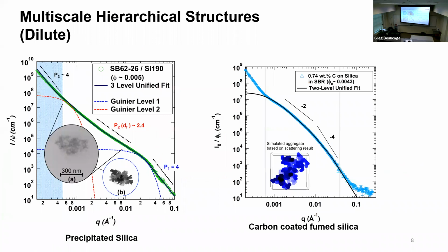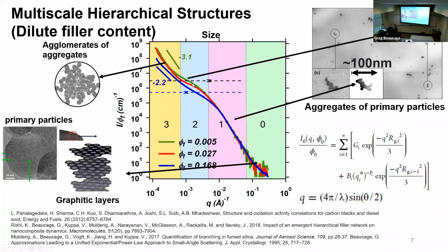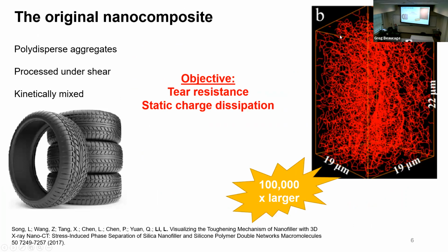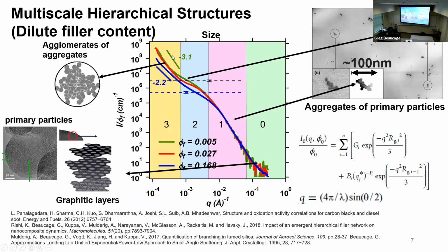Basically the aggregates overlap, that leads to this diminishment, and the speed of that diminishment with concentration tells you how well the particles mix, right? And at the same time, at the large scale, these are the fractal dimensions. So this is solid clusters at low concentration. At high concentration, 2.2 means you've reached some kind of network forming. So it's a low dimension, some random dimension of a network that forms. So in scattering, you can pick out the different levels if you want to simplify things and think about it that way. It's possible to do it.